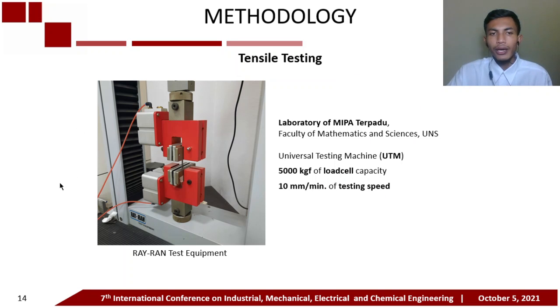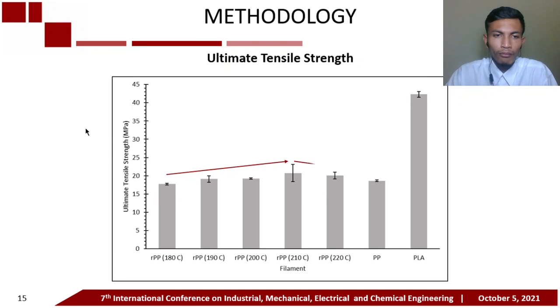The tensile test used the Universal Testing Machine or UTM owned by the Laboratory of MIPA Terpadu, Faculty of Mathematics and Sciences, UNS. The test used a load cell capacity of 5,000 kg force and a testing speed of 10 mm per minute. The data was then collected in a table.